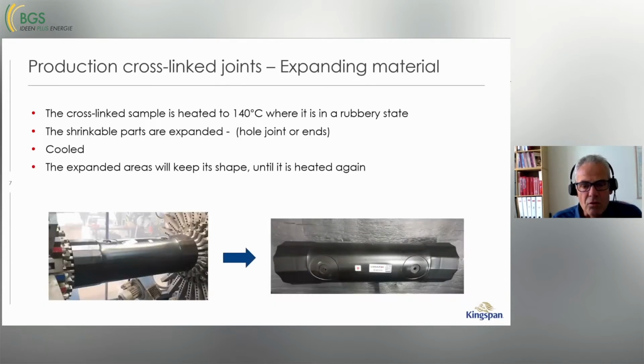When we receive the cross-linked samples, we will heat the samples up to 140 degrees, so the material will get into a kind of rubbery state. The shrinkable parts are expanded, like you can see in the picture to the left, either on the whole casing joint or at the ends, but it will be expanded where it's intended to shrink when we, during the installation later in the project, will heat it. The expanded areas will keep their shape until they are heated again. So it will cool and then it will keep its shape.